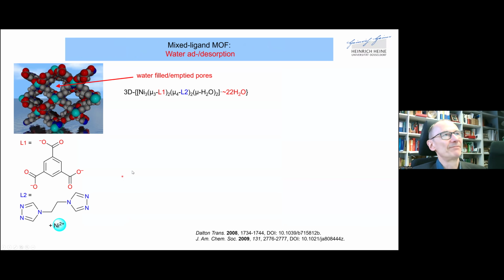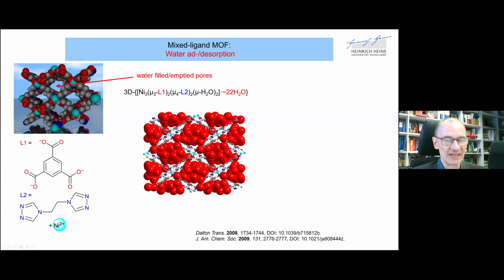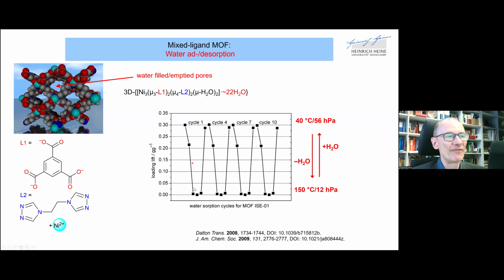So we actually came into this field through a MOF synthesis from water, and this MOF formula is not important for the moment here, that had a lot of water molecules incorporated in the network. So here you see the water molecules in space-filling mode within the framework. And we realized that these water molecules could be removed and reabsorbed over 10 cycles, 4 of them are shown here, without loss of water uptake capacity. So by varying the temperature and the water partial pressure, the water is removed with increasing temperature and lowering the water partial pressure, and brought back in by lowering the temperature and increasing the water partial pressure.